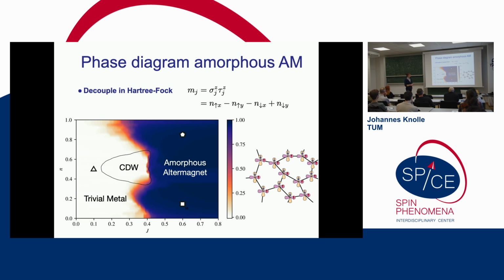But we relieve that by basically having a ferromagnet on one of the orbital directions, and a ferromagnet in the other orbital direction. And the only other interaction that would frustrate you, they are basically chosen such that locally you always basically have the antiferromagnetic only locally arranged. So it's really the fact that we start with a Q equal to 0 order. It doesn't know about geometric frustration.